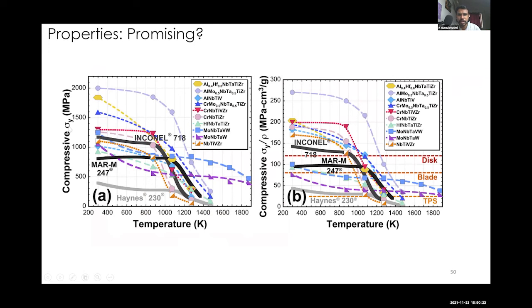Here, compressive yield strength versus temperature is drawn. Inconel, which is the famous nickel-based superalloy, is here, the red line. MAR-M 247. Okay, that is another superalloy. Haynes 230 is another superalloy. These superalloys are here, and these lines with these kind of circles and these yellow symbols, these are for certain high entropy alloys. You can see which is the high entropy alloy here. Okay, they have much higher properties compared to superalloys, and even the temperature capability.